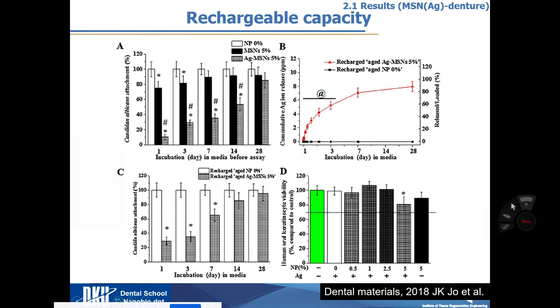And then as a long-term assay, over 28 days, I continuously check their Candida albicans attachment. They are a little bit increased over time, but still they are decreased compared to without nanoparticle. And then I can successfully recharge the silver into denture over 80%. And then I check one more time after recharging. We can expect that the oral keratinocyte viability is a little bit decreased with silver, but almost similar. So I can say that when the denture incorporates this silver nanoparticle, it can show decreased Candida albicans attachment, and then we can recharge it for maintaining this efficacy.